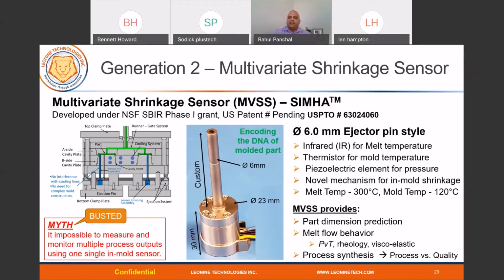So we use infrared technology for the melt temperature, a thermistor for the mold temperature, piezoelectric for the cavity pressure, and a very new mechanism, other than the single mode, for the in-mold shrinkage. This sensor can operate up to 300 degrees C melt temperature and 120 degrees C mold temperature, so it covers a very wide material range too. What you can get is the part dimension prediction, and you can also derive the PVT behavior, the rheology, and further the viscoelastic behavior. It will provide the complete process synthesis for process versus quality, which the current sensors are not capable of doing.